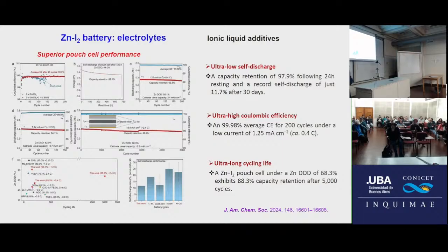Okay, finally you can see the very high DOD, zinc utilization is over 68%. So very high already. We can run 5,000 cycles. How about other studies? You can see the highest performance is 500. So 5,000, 10 times. Okay, high DOD is better, right? Our DOD, I just mentioned, is 68 already. Only one publication is higher, but it can run only 50 hours.